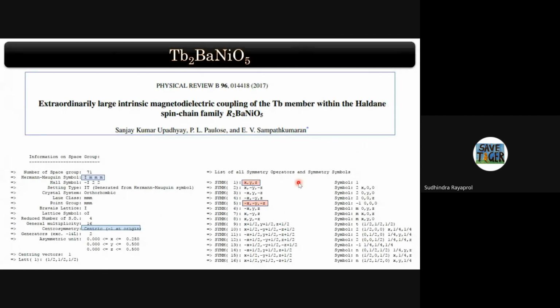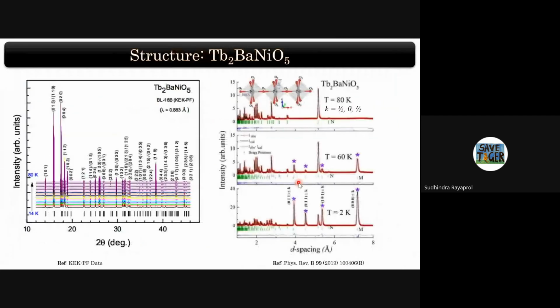So from the crystal structure point of view, this is not supposed to show a ferroelectric transition, but yet we see that. Second, we wanted to see if there is a temperature-dependent change in the crystal symmetry, which was not the case. And when we do magnetic structure determination, we find that the magnetic order sets in at 60 Kelvin. That is where the first ordering temperature was observed. Below that temperature, you see magnetic Bragg peaks which evolve.